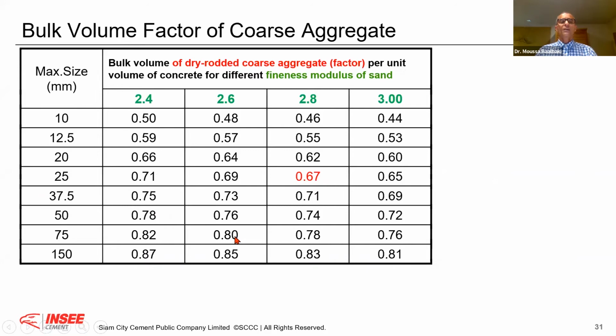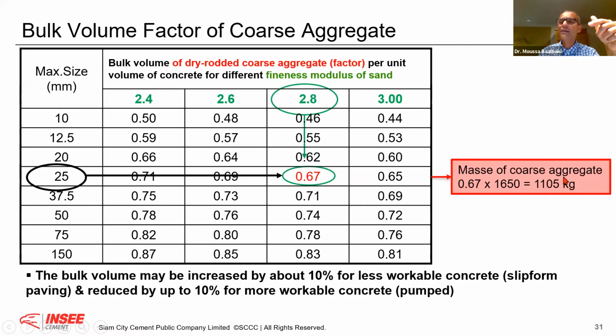Now, you see, this is a table that gives you what we call the bulk volume factor for the coarse aggregate. What you have in green here is the fineness modulus. Therefore, you need to know the fineness modulus of your sand. I know it. Now, I should know the maximum size of aggregate, and I know it. Therefore, for example, with a 25 millimeter aggregate and a fineness modulus of 2.8, I have a bulk volume factor of 0.67. I will multiply this factor by the dry rodded bulk density, which is 1,650 in the case we have seen. Therefore, in my mix, if I take this sand and this specific aggregate, I can go to 1,105. Sometimes I cannot go more than 1,000 even. This is why this factor is very important.